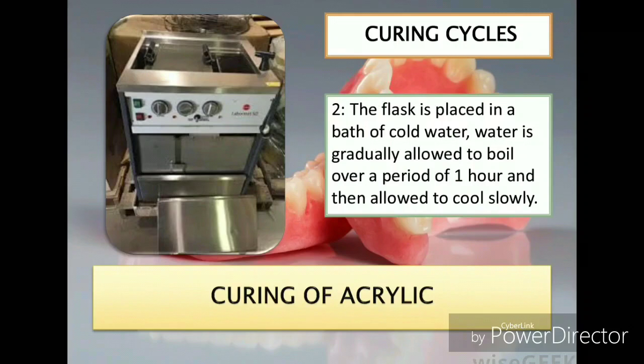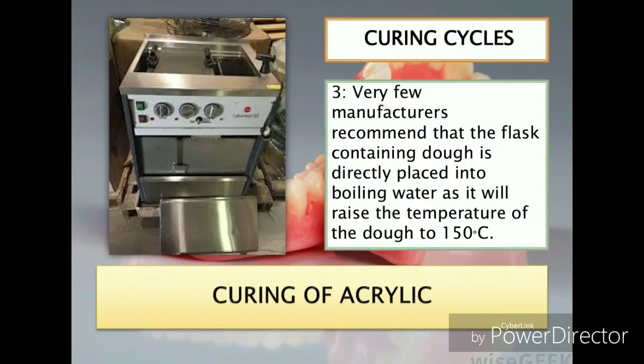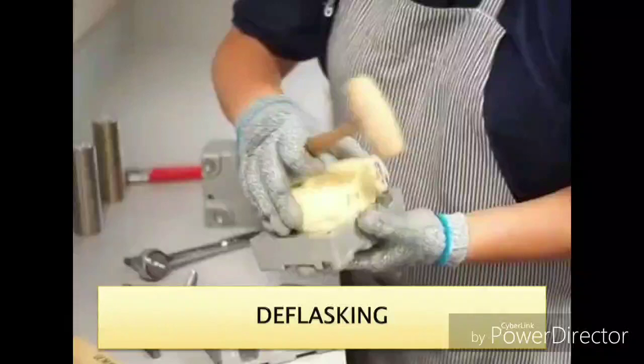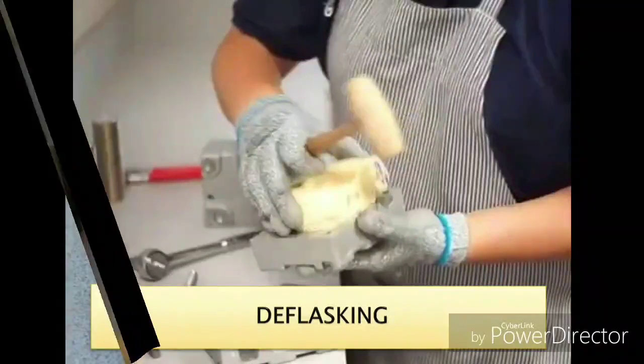The third type of curing cycle is the one in which the flask containing dough is placed directly into the boiling water. Well, this type of curing cycle is not at all recommended by many manufacturers, and it can raise the temperature of the dough up to 150 degrees centigrade, which is not at all recommended. Out of these 3 curing cycles, only the second curing cycle is recommended by most manufacturers for the heat cure acrylic resins. After curing, the deflasking is done, in which the gypsum mold is taken out of the dental flask.